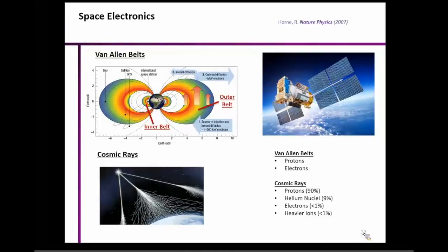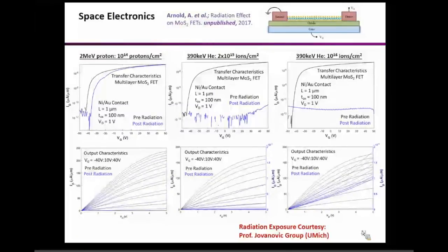Some of our initial results actually show that if you use a 2D molybdenum disulfide transistor and expose it to a 2 MeV proton with a fluence of 10^14 protons per centimeter squared, you maintain the characteristics. Of course, there is a certain shift in the threshold voltage, but that's actually the problem with the oxide. That's really not the problem with the 2D material, because the 2D material is so thin, it's almost invisible to the radiation. That's why the material is not getting degraded. It's just because we are using a thick oxide for our demonstration, and the oxide is getting affected.